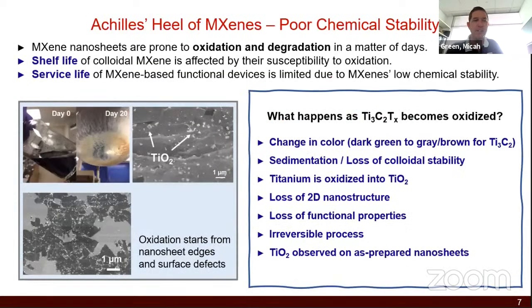What that means is a lot of these MXenes, like Ti3C2, will actually oxidize in water. They turn into TiO2. You'll see them change color. You'll see them come out of solution. And that means you lose their properties. You lose that 2D structure. And so for those of you who work on graphene, imagine your graphene went bad 3 days after you made it. Those are the kind of problems that the people in the MXene community are facing.